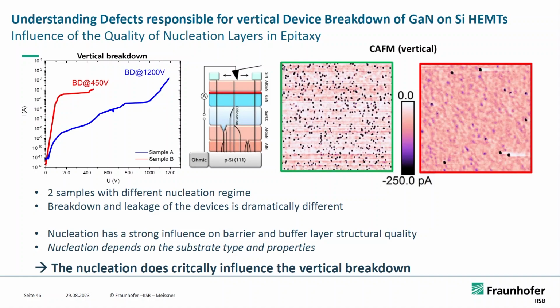And now we did an experiment with a conductive AFM measurement. So you have this structure here, and you measure with the AFM tips from the top, and you make a potential between the AFM tip and the backside of the substrate. Now you scan along your surface in a small area, and you see all such spots where the AFM tip is measuring continuous leakage current, measuring the current through the structure.